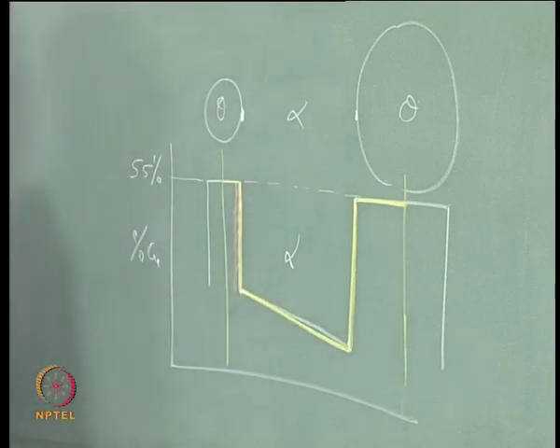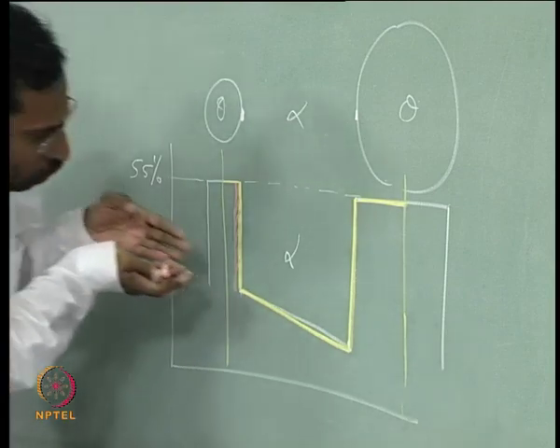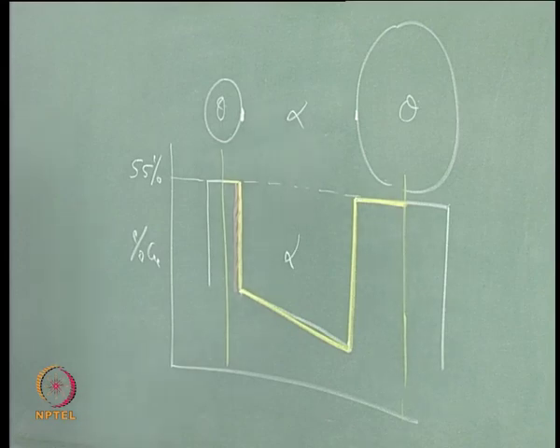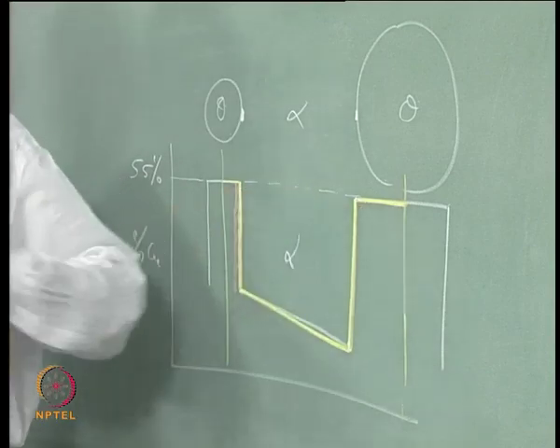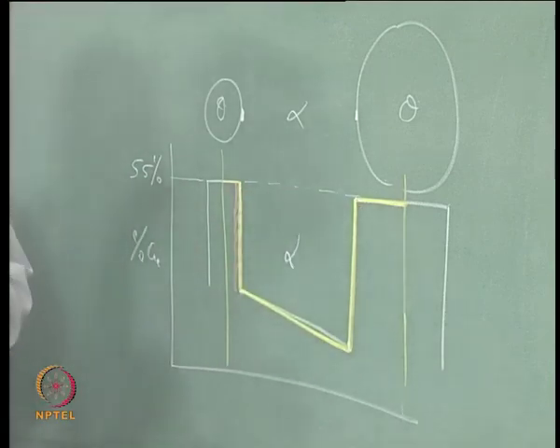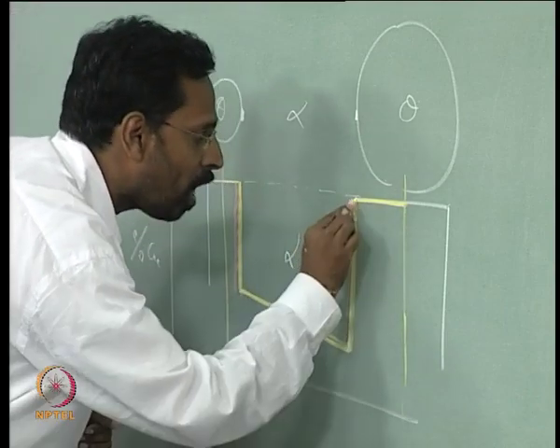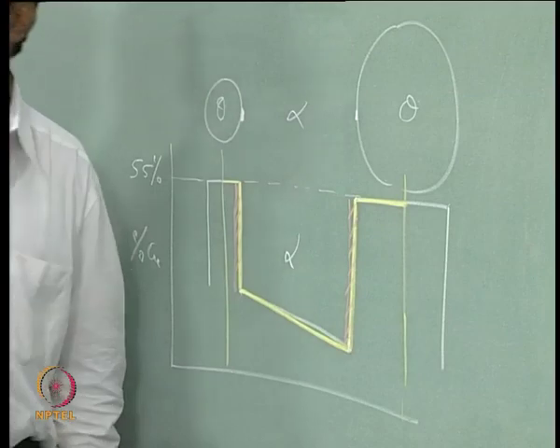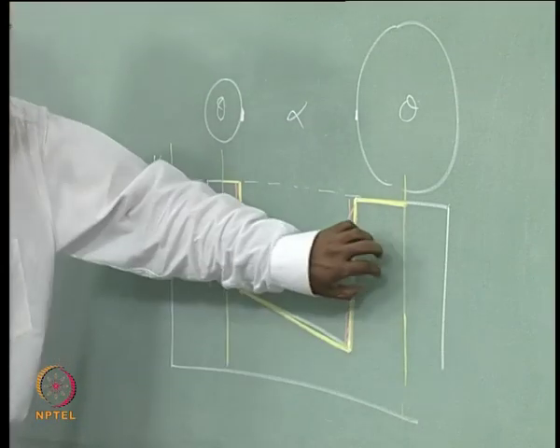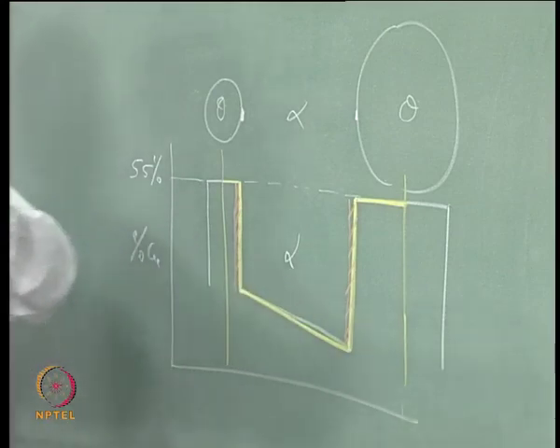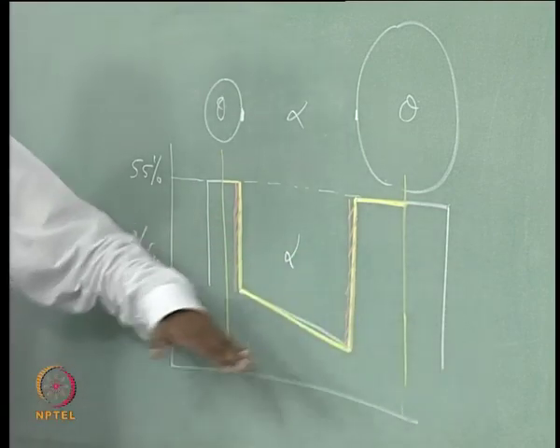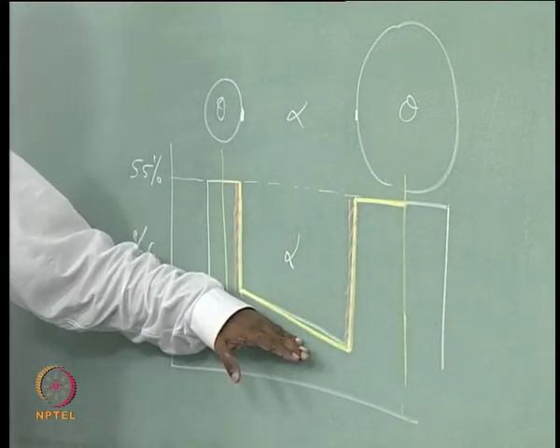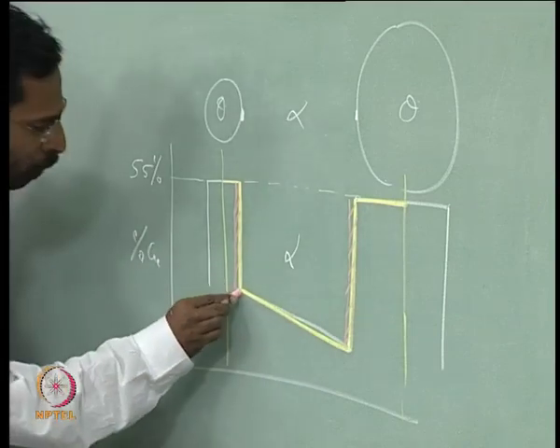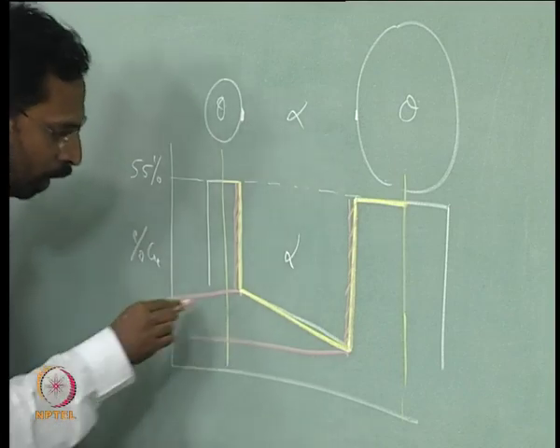If it dissolves, let us say, what happens? Some copper atoms are released, and those copper atoms will move down this concentration gradient and come to this region, and once they reach that region, this particular theta needs copper atoms for it to grow. So, it provides copper atoms. Once the copper atoms come towards this, they join this particular theta, and the theta grows by a small delta x, depending on how many copper atoms have come and joined. So, this gradient will more or less remain the same, excepting that the concentration values, this value and this value, what do these two values depend on?